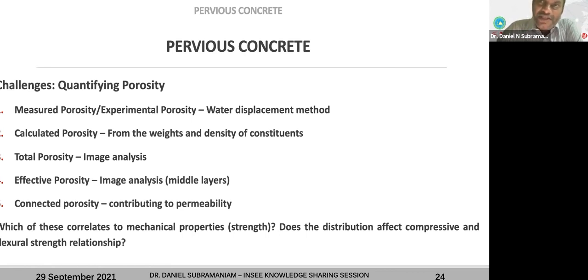Measured porosity is the standard method where you dip the concrete into water and measure the volume of water that is displaced. From that, you can find the amount of porosity. The calculated porosity is where we calculate the volume of pores depending on the volume of constituents that we used. We know the mass of each constituent that we used, and we divide that by the density to get the volume of each constituent. Then, if you deduct these from the total cube volume, you get the volume of pores. For total porosity, we are using image analysis, which I will explain later.